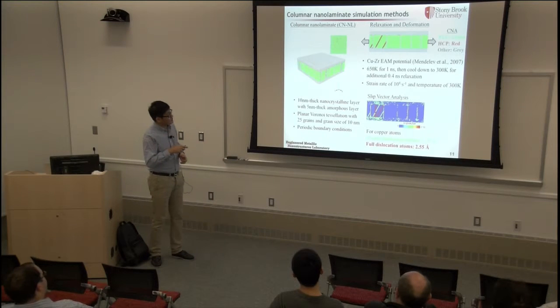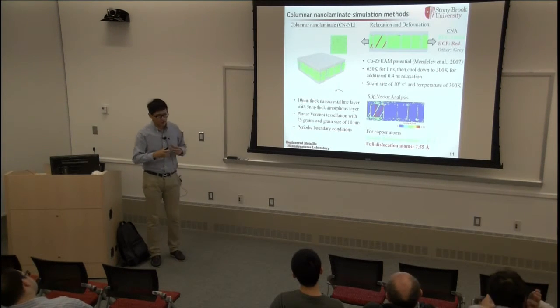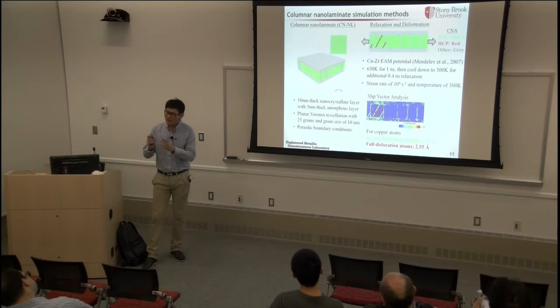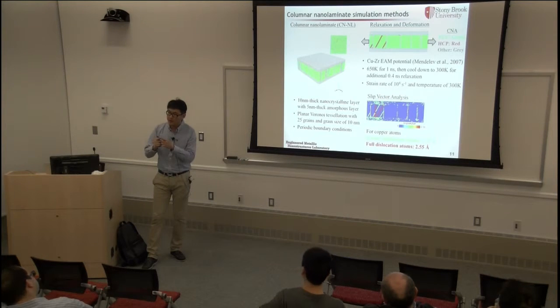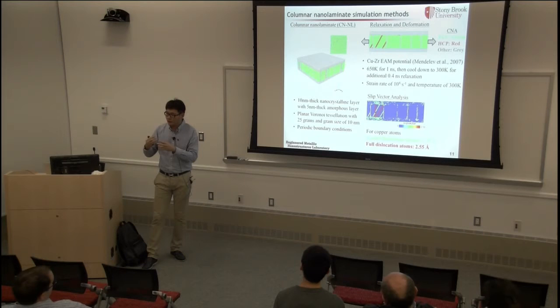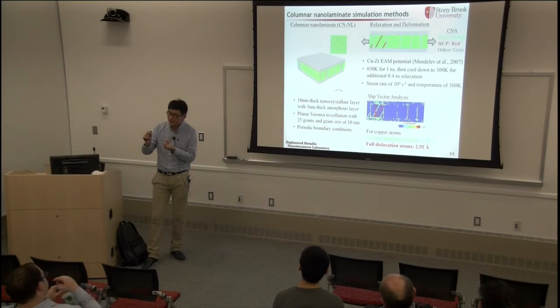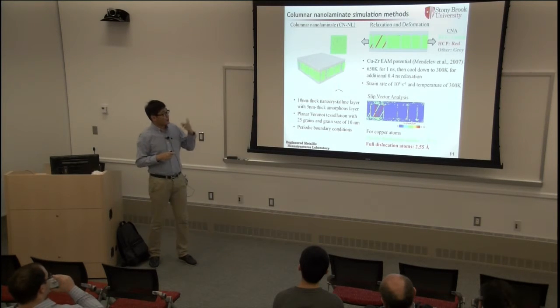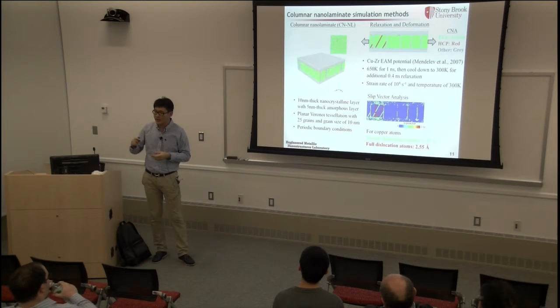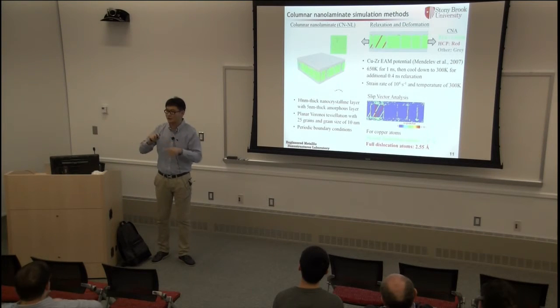And actually, for the grain size here, it's not a random orientation or random grain size. We modify this because we use the Voronoi tessellation. You're going to have a really small, acute angle between the two faces. When we impose a small separation distance between one Voronoi seed and another, we get rid of those really small acute angles in the material. It also imposes a smallest grain size and gives a really narrow grain size distribution.